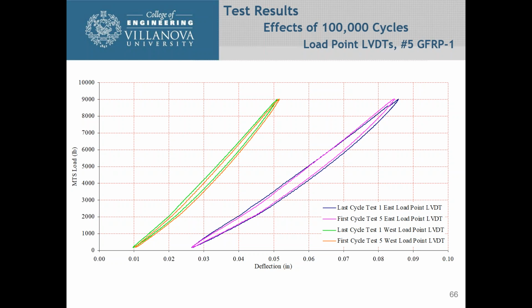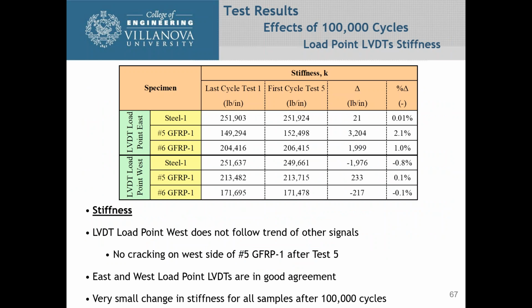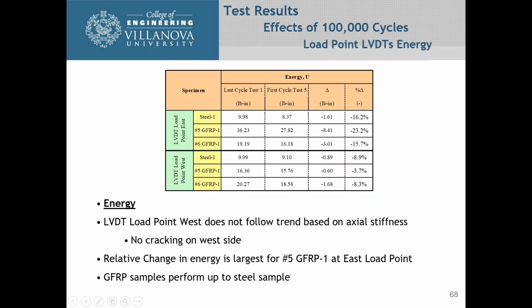The next thing we want to look at is at the load points, how much deflection we were getting. And if you compare the black and the magenta, you can see that after 100,000 cycles, the curves almost fall right on top of each other. So what that is essentially telling us is that there's very small change in the stiffness of the member due to the 100,000 cycles, because at the load points you're deflecting almost the same as if you were without the 100,000 cycles. And again, the change in energy is largest for the number 5 bar at the east point. We had a lot of issues again with data collection, so there's some information that doesn't 100% jive here.